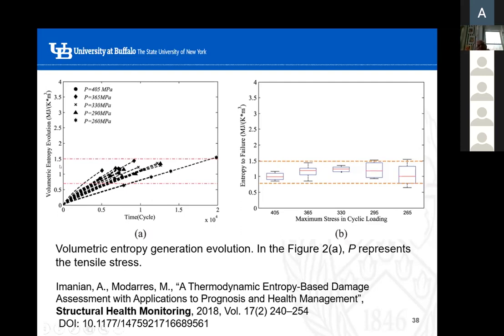Now, you might say, how come there is not a single value at the failure, but a band? Because when you do an experiment, you are not actually testing exactly the same samples, okay? The next sample will have different amount of dislocations, will have different boundary conditions. There will be always variation from sample to sample. Little bit, but not much. So if you look at the band, it's a very narrow band.